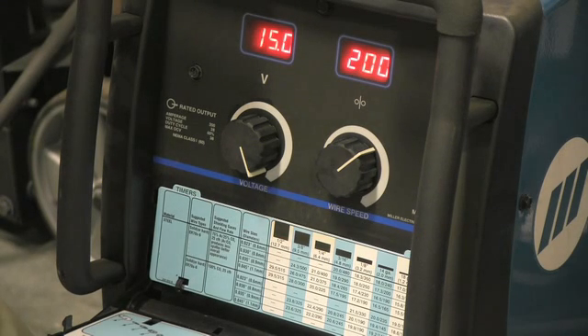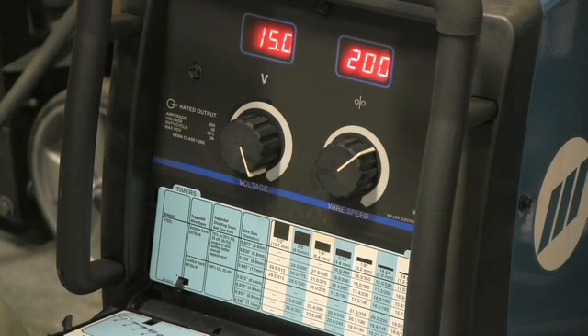But you have a wire feed speed setting. And wire feed speed in the gas metal arc welding process is also adjusting the welding current. So how do I know what wire feed speed coordinates with what amperage? That's a good question. Well, there's some multipliers out there depending on the size of wire that you're using. So if you're using an 035 wire, then you'll want to multiply by 1.6. That's the multiplier. Multiply the welding current by 1.6.